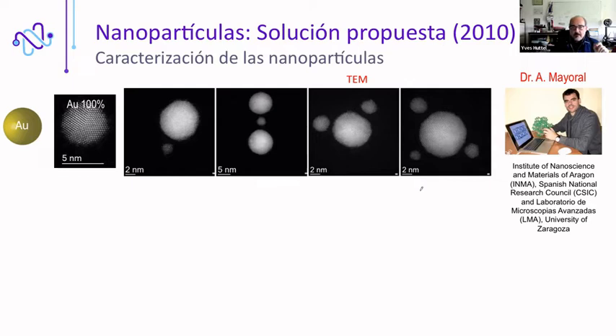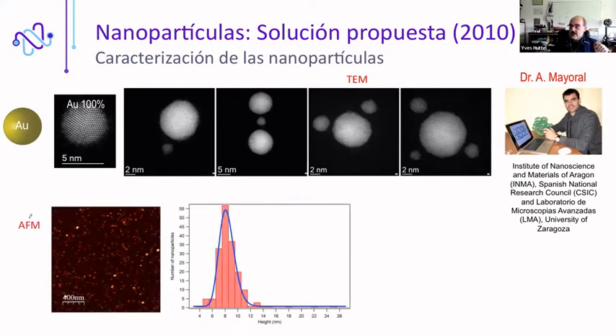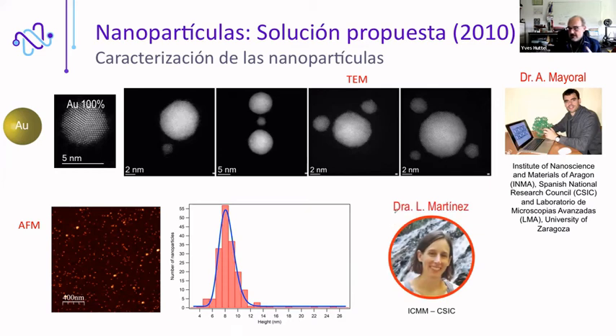So what we use is an AFM, atomic force microscopy. This is our routine tool to characterize the nanoparticles. But you clearly understand that the resolution is not as good as a TEM. And here I thank my colleague Lydia Martinez, who is the expert in the group, who makes the AFM images. And I would like to say that when we started to make very small nanoparticles, Lydia started to complain because she could not measure them with the atomic force microscopy. So we were facing another problem. We wanted to make small nanoparticles, but we were not able to characterize them except using the TEM that is more expensive, of course.